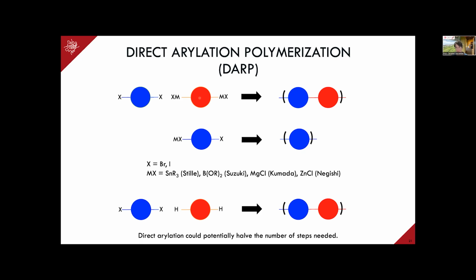But in the case of direct arylation polymerization, or DARP, the idea is that one of the monomers would be completely unfunctionalized. So you just have a CH bond. And the idea here is that you would still be able to react these two monomers and obtain the polymer. This is a great way to synthesize polymers because, first of all, going from this monomer to here is usually a two-step synthesis. So if you don't have to make this at all, you save the number of steps involved in the overall synthesis. But also, doing this synthesis, you have to use a stoichiometric amount of these organometallic reagents. So you also save on a lot of the reagent as well.